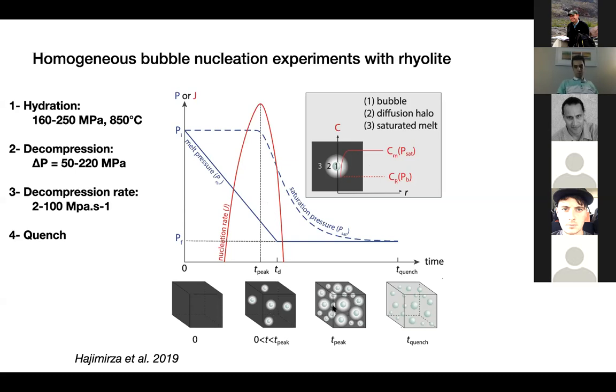As more bubbles nucleate in the system, and these diffusion halos also grow, at some point these white regions cover the whole sample, meaning water concentration starts decreasing throughout the sample. At this point, saturation pressure starts decreasing, nucleation rate peaks and drops quickly. Nucleation rate stops, and samples eventually reach equilibrium.